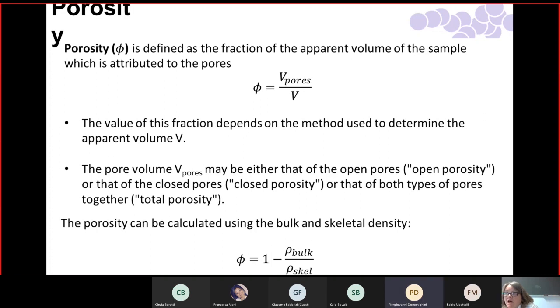I think what the measurement you make is indicating is something about the volume of closed pores, right? And also the silica, depending on what you do, if it sinters a little bit, if you heat it, it's going to be a little different, right? It's going to be a little denser. So we know the upper limit, we know what we measure, and what you measure can tell you something about closed pores in there. What percentage is closed in the system.